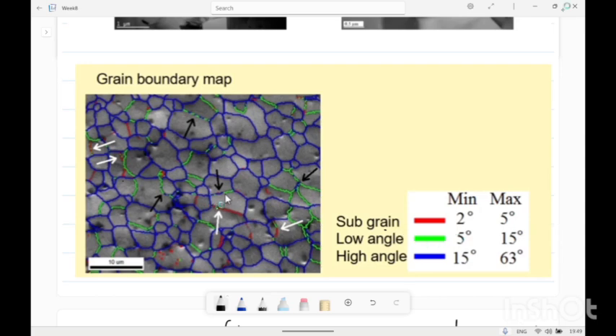Means with the rearrangement of dislocations, the subgrain boundaries transform into low angle grain boundaries, and the further rearrangement of dislocations and rotation of grain boundaries lead from low angle grain boundaries to high angle grain boundaries. So the transformation can be seen. In this grain, initially it was a single grain, but due to the formation of subgrain boundaries, it is divided into two grains, while the subgrain boundaries are also slowly transforming into low angle grain boundaries. That is shown by this transformation of red to green.